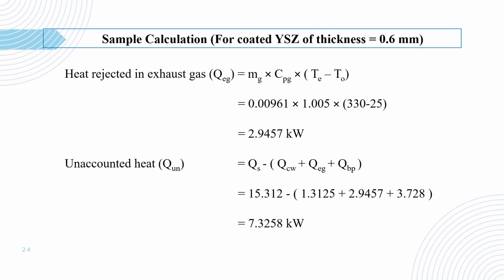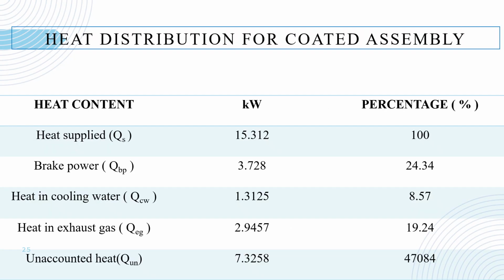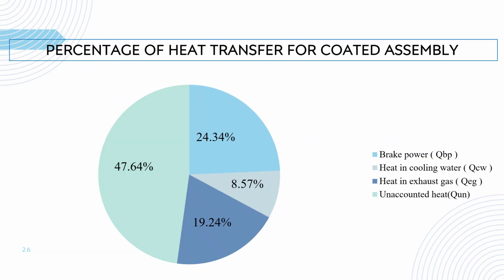As we can see, we have done the same calculation for our coated piston as well, the one that we did for the uncoated one, and we have found the same parameters, that is heat in the cooling, heat in the exhaust gas, the brake power, and the unaccounted heat. And this is the table for the coated assembly. As you can see over here, the exhaust gas temperature, percentage-wise, has increased as compared to the uncoated one. Here is the percentage breakdown for the same.